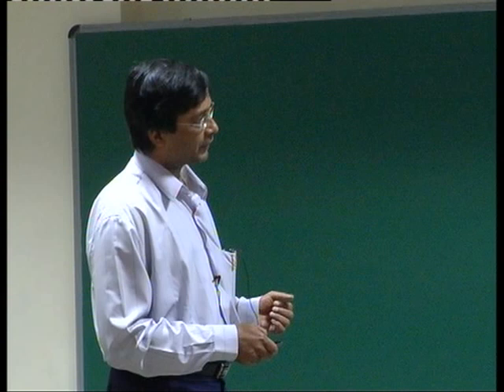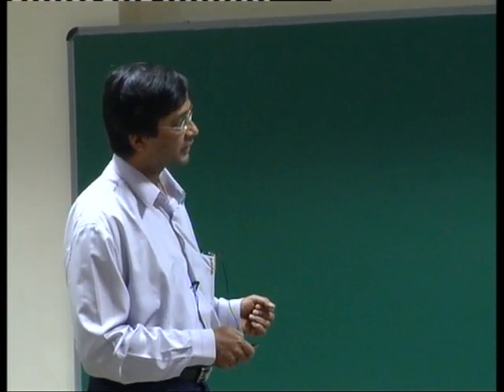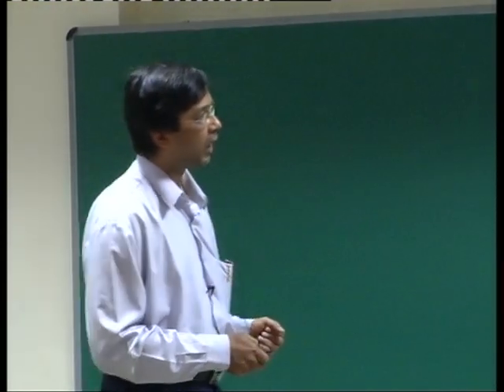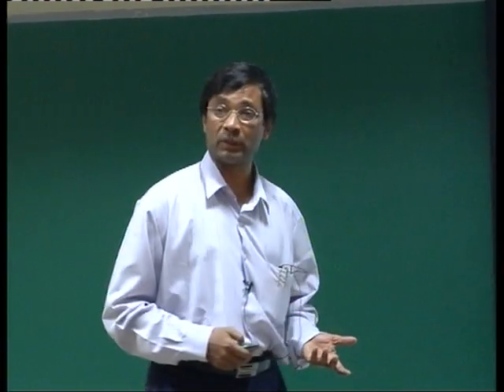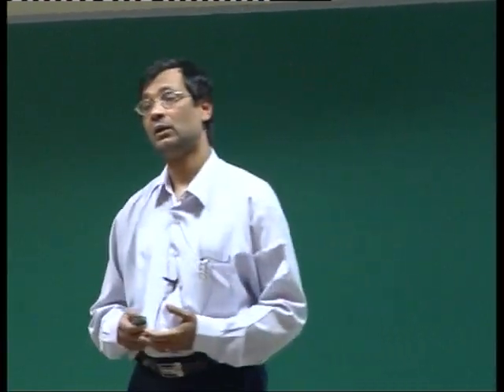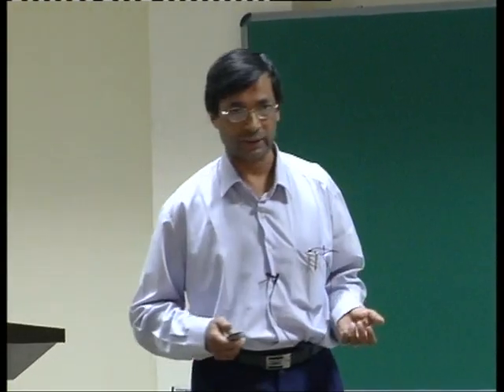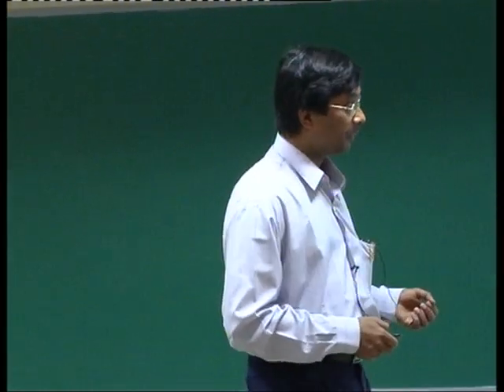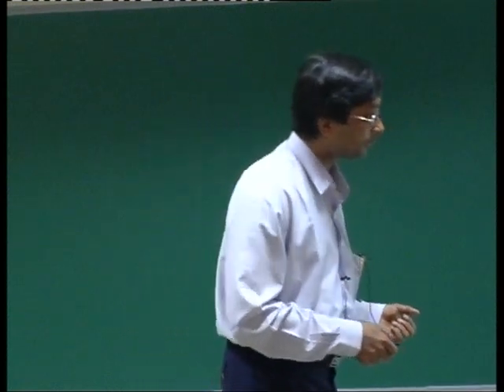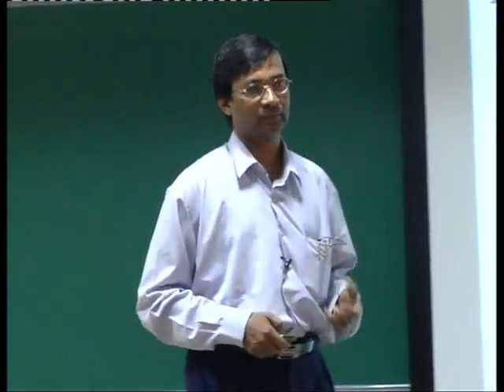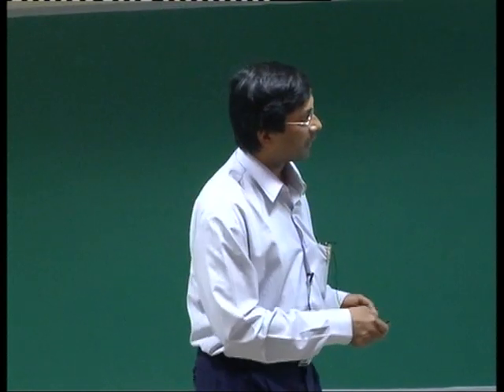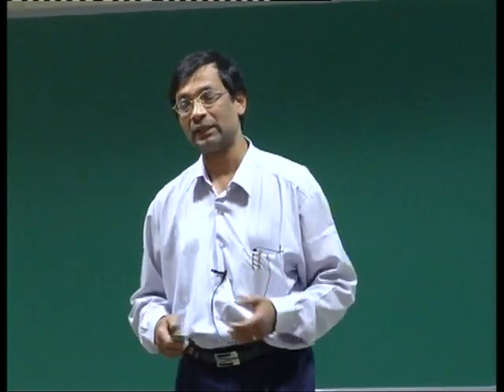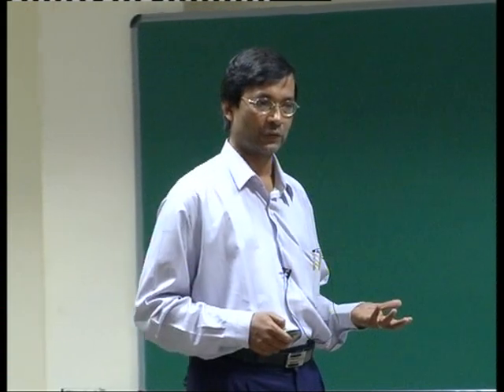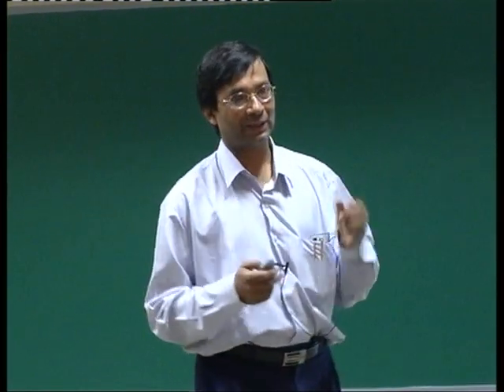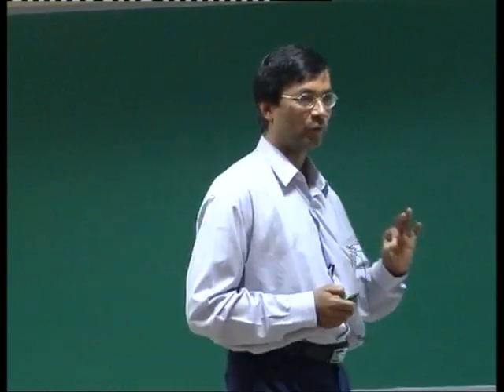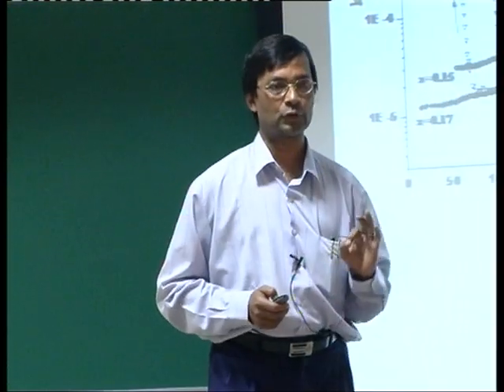So one would say, well, if I convert it into carrier density, it's in the order of 10 to the power 20, 10 to the power 21 per cc, which is not such a small number. This number is pretty good and would be some kind of a metal, not an insulator. But then, immediately, somebody did what Vijay was asking me, with this data, to plot the carrier concentration as a function of x, the concentration. And when they linearly extrapolated it to zero vacancy concentration, they found that the carrier concentration also gets very close to zero.